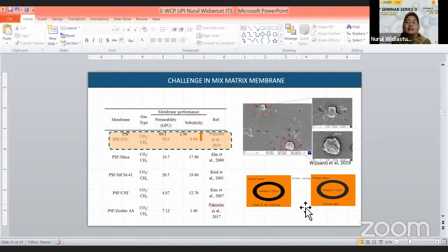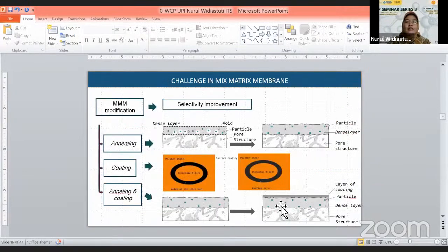So that's why we are trying to improve the performance of the mixed matrix membranes with different kinds of methods called annealing and coating, and also we combine the annealing and coating. We hope that these methods will decrease the voids at the interface between the inorganic filler and the polymeric phase, so it will reduce the voids and also improve the selectivity of the membrane itself.